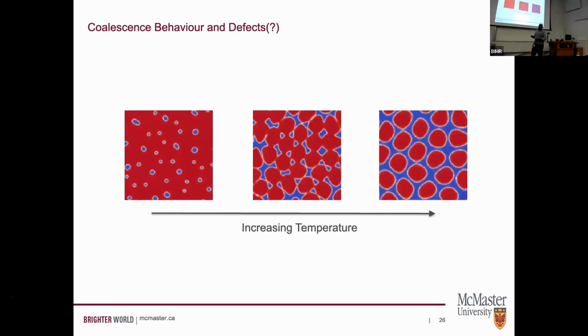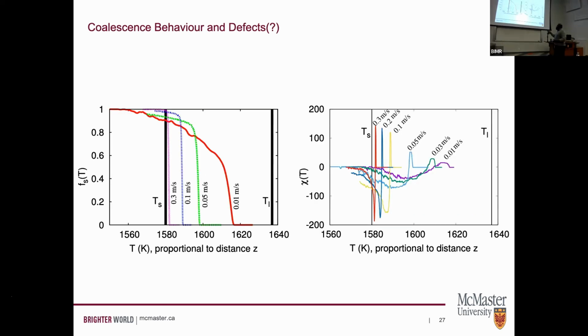We've also looked at how things are coalescing in this system. So we find that with increasing temperature, as you'd expect, you should have more liquid regions in your system. And how do you track that? And so we used the Euler characteristic here to see essentially how connected our system is as a function of temperature.